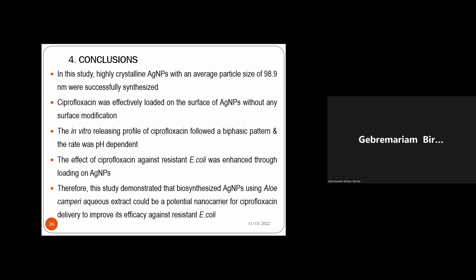The in vitro release profile of ciprofloxacin followed a biphasic pattern, with an immediate drug release and a continuous, sustained drug release of the product. And the effectiveness of ciprofloxacin against resistant Escherichia coli was enhanced through loading on silver nanoparticles. So loading of the antibiotic on these silver nanoparticles has a significant effect. It improves the efficacy of the desired antibiotics.